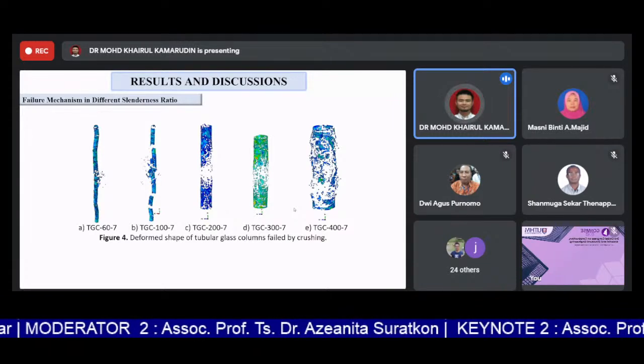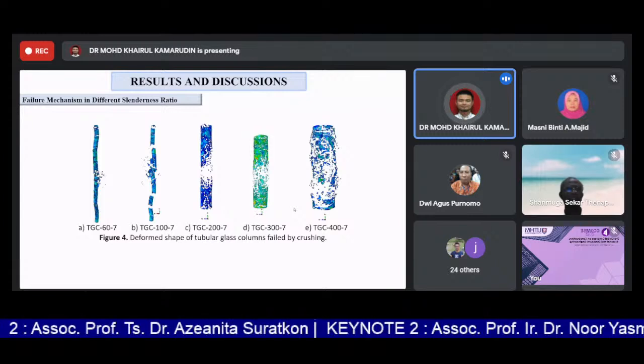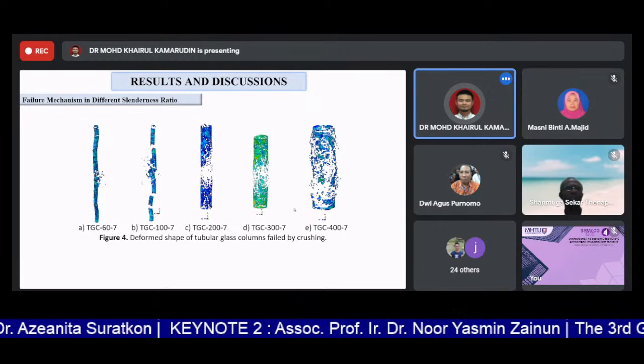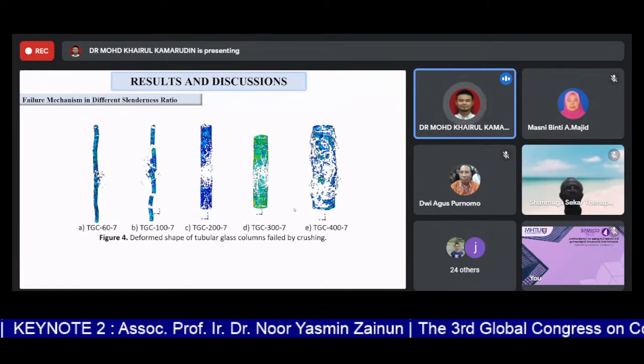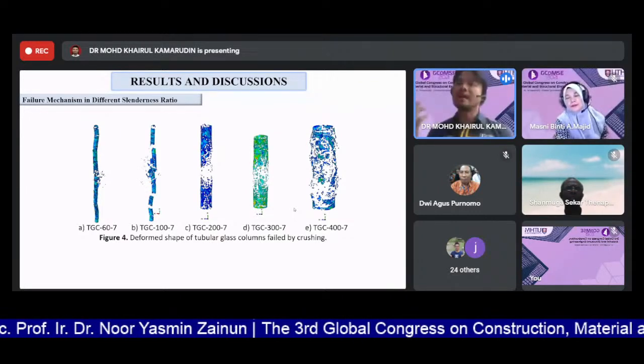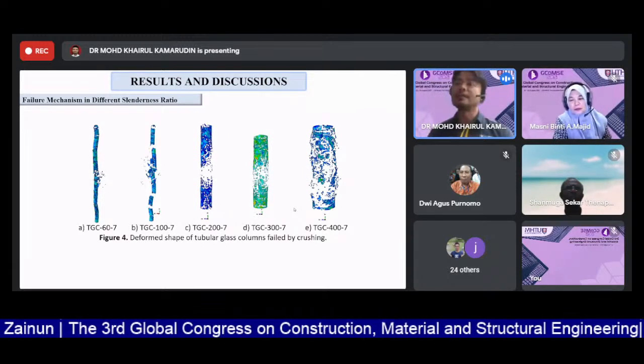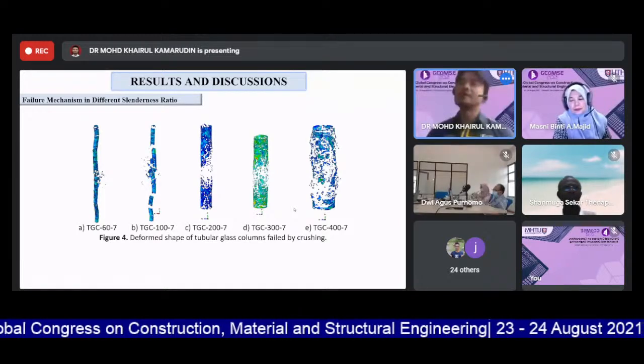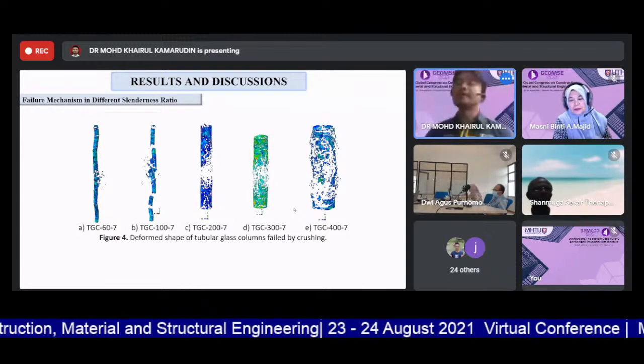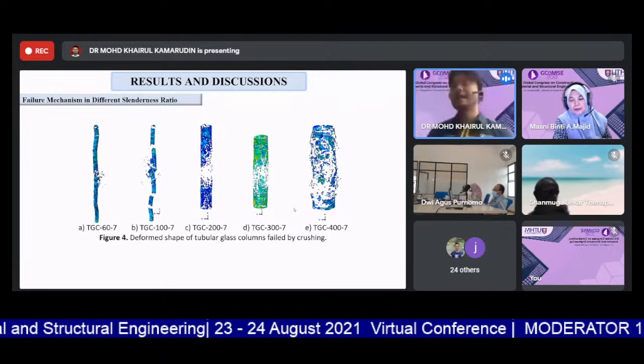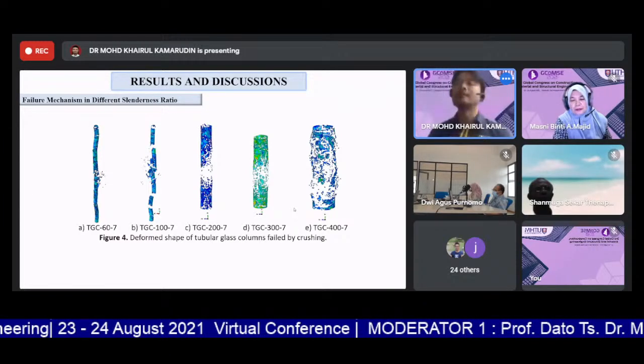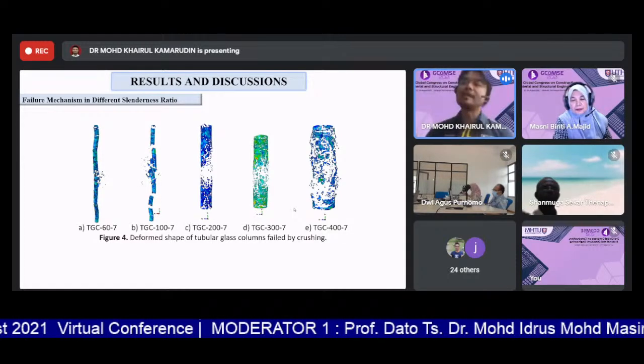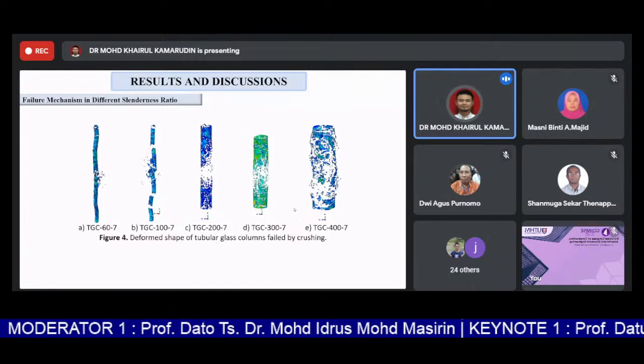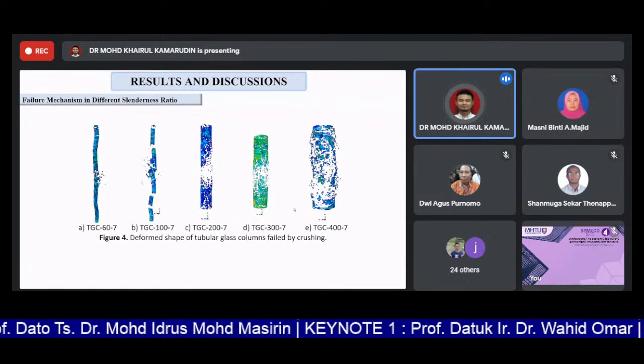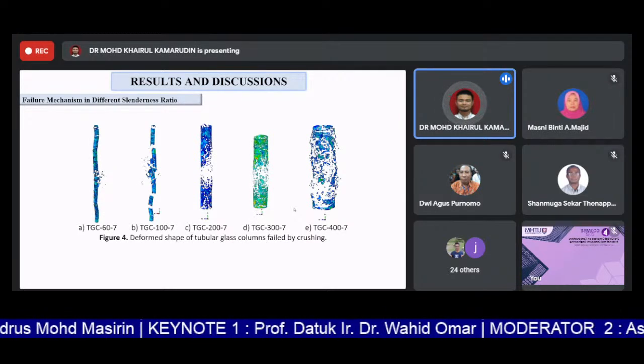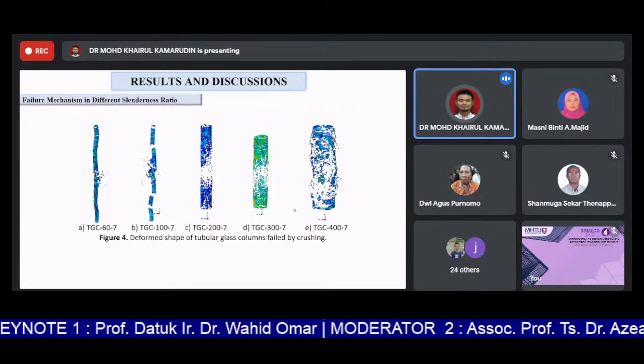When we conduct this analysis, the first part, when we look upon results, is in terms of the failure mechanism. We managed to identify 2 different characteristics for the failure mechanism. When we have a smaller or lower slenderness ratio, we expect the glass column to fail under crushing. But when we have a slenderness ratio more than 40, the failure predicted is in terms of buckling failure. This is comparable to what we had from the experimental work previously, as the same constant 40 slenderness ratio is a benchmark to give us the result whether the glass column fails either by buckling or crushing.